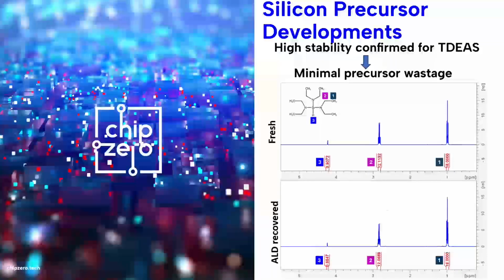That means we were able to continuously use this precursor, and even after multiple ALD runs, this precursor remained highly stable. As you can see in the NMR, before and after the ALD, there is no change in the precursor. So in a way, these precursors are highly useful from the ALD point of view, or from the semiconductor industry point of view.